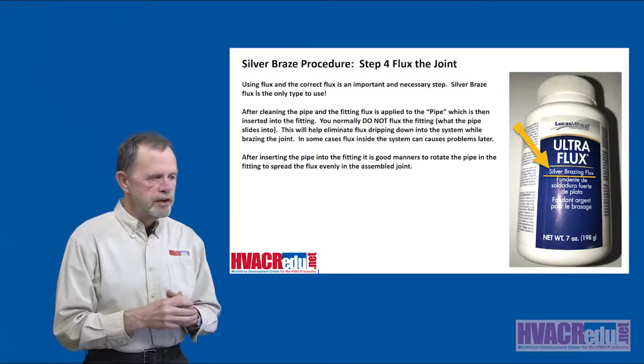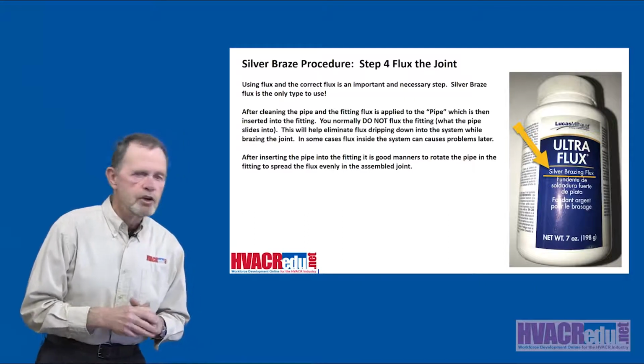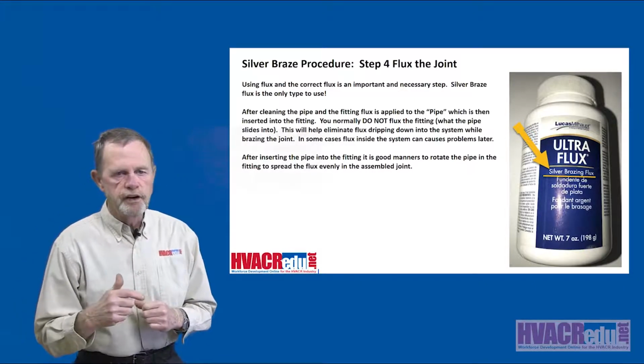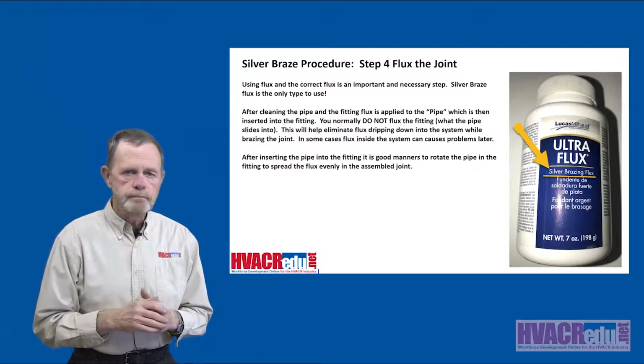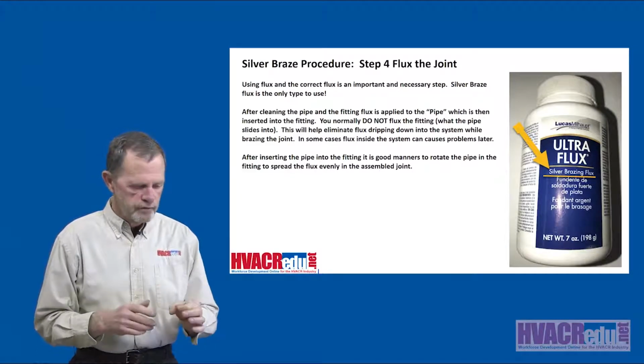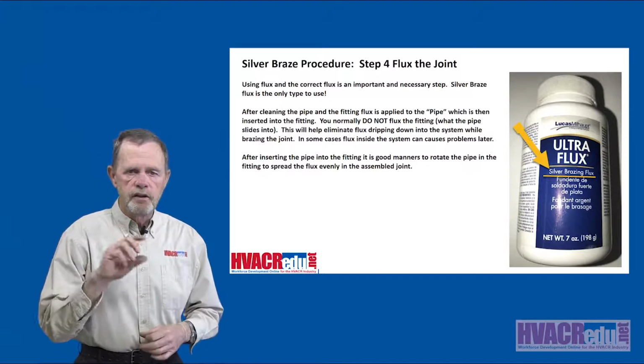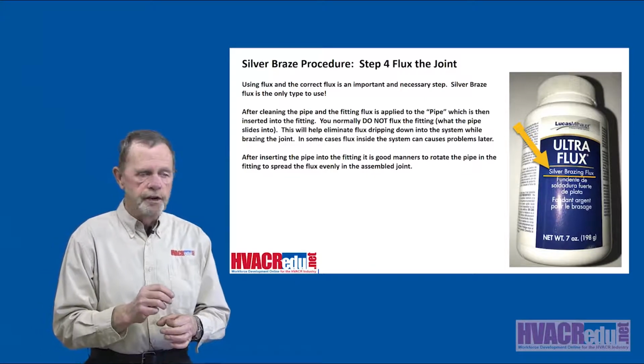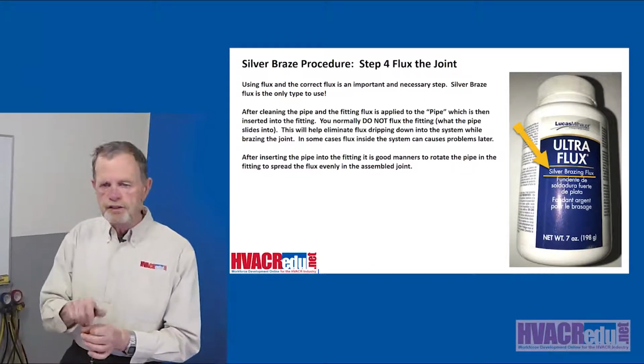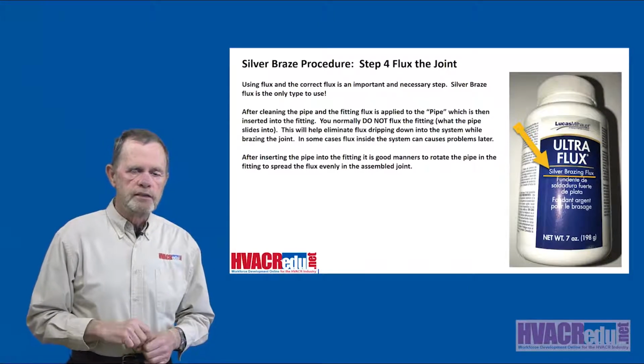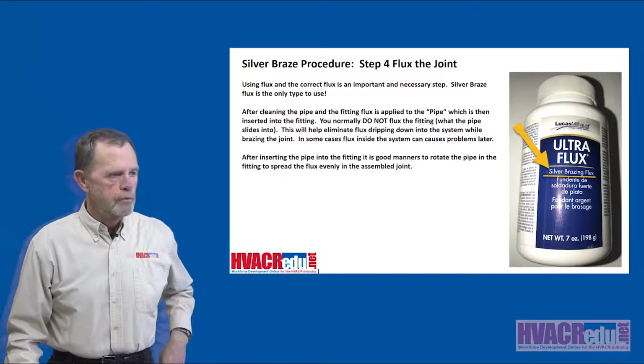Now, another thing to know about fluxing is you flux the pipe, not the fitting. You flux the pipe, not the fitting. In other words, you don't flux the inside of the fitting. You flux the pipe that's going to insert into the fitting and then twist it maybe a little bit to smear it around inside the fitting. You should be good to go.